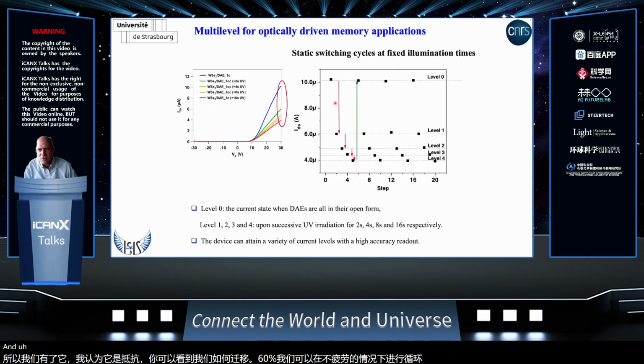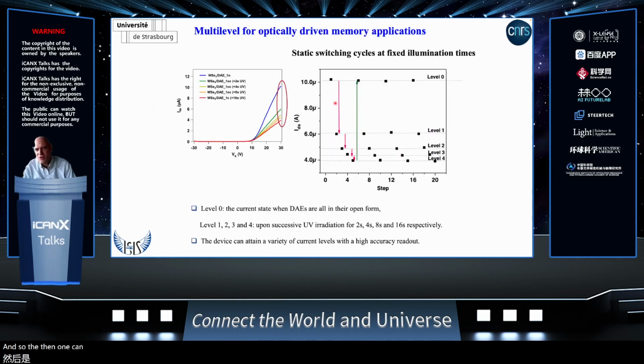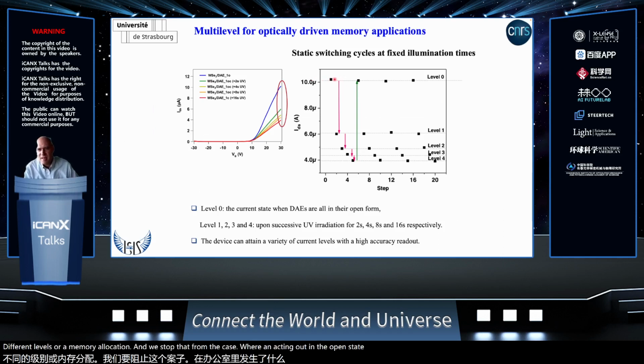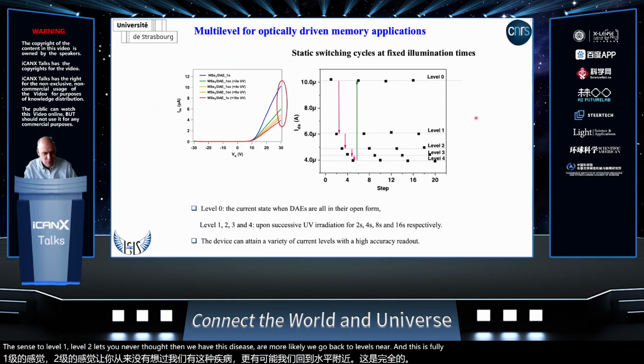And so then one can just show here a very simple cartoon of how we can access different levels for a memory application. We start from the case where the diarylethene is in the open state. That is the case of level number 0. We irradiate successively for 2, 4, 8, and 16 seconds of UV light to access level 1, level 2, level 3, level 4. Then we irradiate with visible light, and we go back to level 0. And this is fully reversible, reproducible.